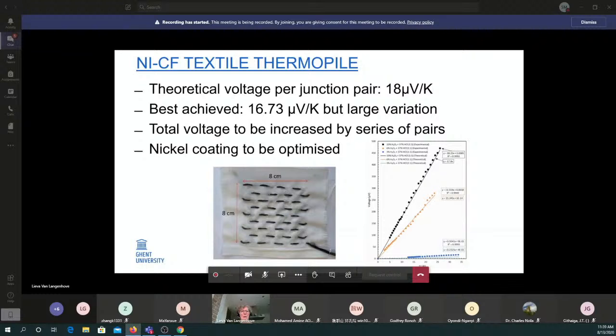Here the yarn has been inserted by hand because the etching has been done at the level of the fabric, and we achieved a thermal voltage of 16.7 microvolt compared to a theoretical maximum of 18, which is an efficiency of more than 90%, which is quite good. And the total voltage can be increased by having multiple pairs in series, which is a linear effect actually.